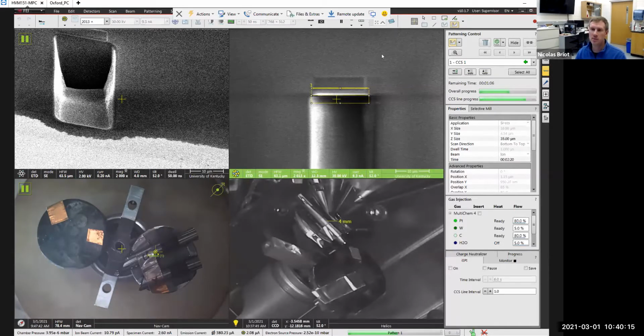One good thing about that cross-section polisher I talked about is that, for example, right now, I coated the surface I told you with that gold palladium alloy, just sputter coated for conduction. That's why you have the change in color here. But as soon as I cut through, I exposed the glass, right? So that's not conductive, of course. Whereas if you made a big cut with the other machine, that sample preparation machine, you can then take the sample and make a quick coating at the surface of that cross-section, and then you go to the SEM and not have problems. Here, if I wanted this to become more conductive, I'd have to vent the system, coat, and then go back. So it's a lot of time for just such a small region, which is one advantage of the machine.